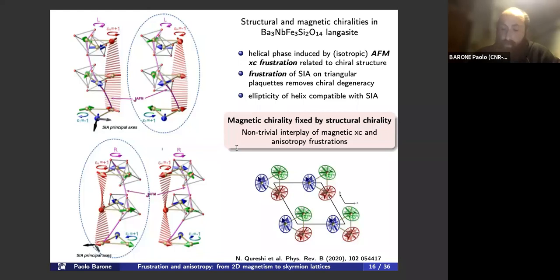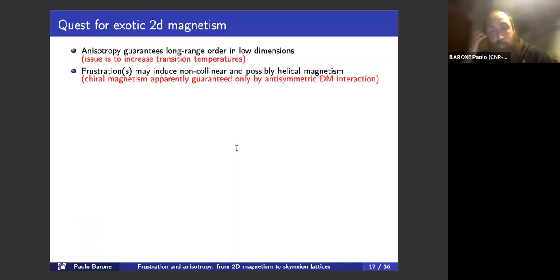Okay, now we have all the ingredients to discuss our quest for exotic two-dimensional magnetism. So we have seen that we need anisotropy to have long-range order in low dimension. This is typically always guaranteed. The main problem is related to the scale of the transition temperature. And the other thing is that we can use frustration, or several kinds of frustrations, to induce non-collinearity and helical magnetism, even though up to now, generally, chiral magnetism is provided only by antisymmetric Dzyaloshinskii-Moriya interaction.